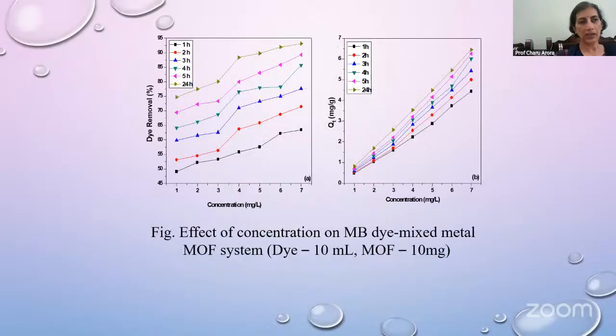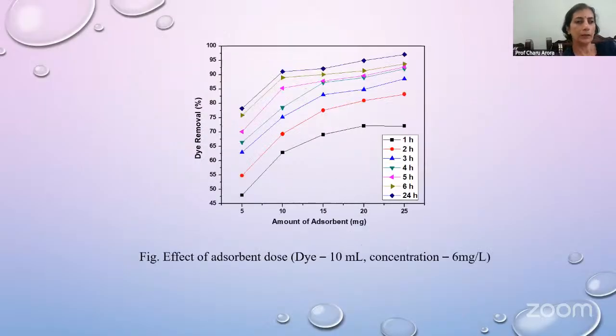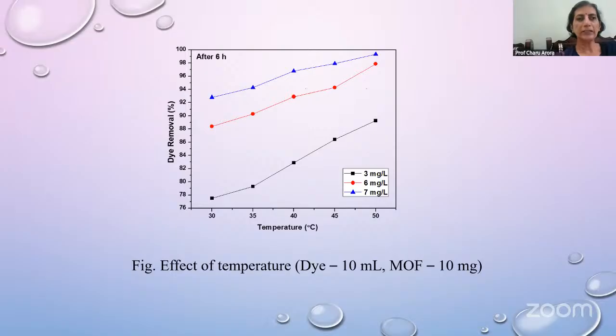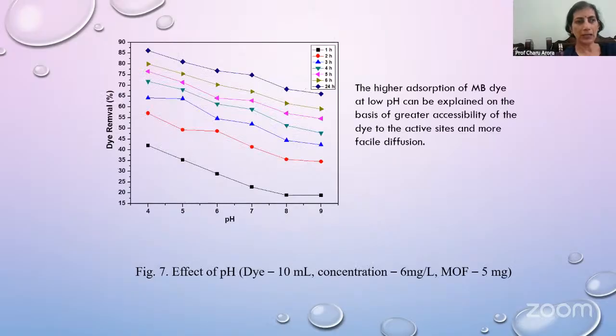Again, you can see the removal efficiency has increased several times while we studied the effect of concentration. The first graph shows dye removal in terms of percentage, and the second graph shows it in terms of Q, in milligram per gram. This curve is showing the effect of dose. You can see with increasing the amount of metal organic framework, removal increases. On increasing the temperature, removal efficiency increases. If we talk about the pH, maximum removal was observed at pH 4.